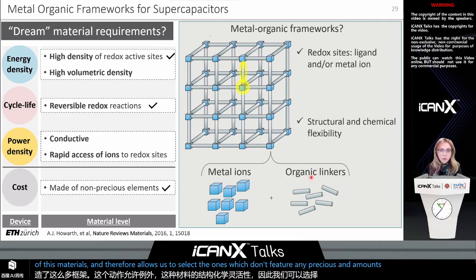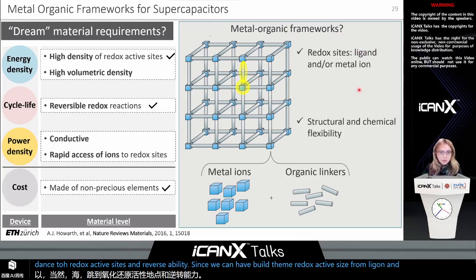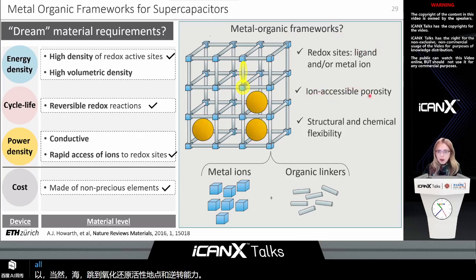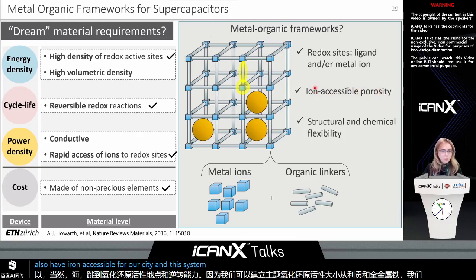Then we can ensure high density of redox-active sites and reversibility, since we can have built-in redox-active sites from the ligand and/or the metal ion. We can also have ion-accessible porosity in these systems, which by design would provide rapid access of ions to the redox-active sites.